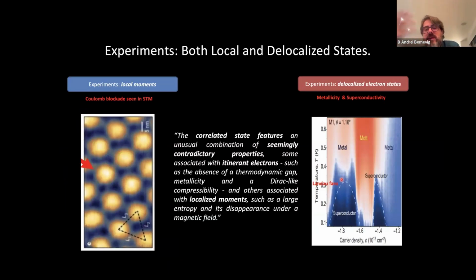So it looks like this system is just highly localized electrons, but we also know from Pablo, from Efetov, from Philip Kim, Andrea Young, many other people, Amir Yacoby, that this system is not just localized states, because localized states could not give me superconductivity, could not give you metallic behavior. So we know the system is very different from localized states, but it looks very strange. In a famous paper, it was basically said that this correlated state features contradictory properties, some associated with itinerant electrons and others with localized moments. I don't have time to go through the details, but what I want to argue is that this system is the perfect quantum simulator for a new state of matter that's called a Mott semi-metal.